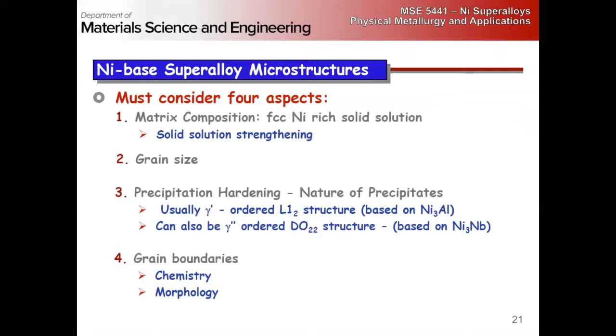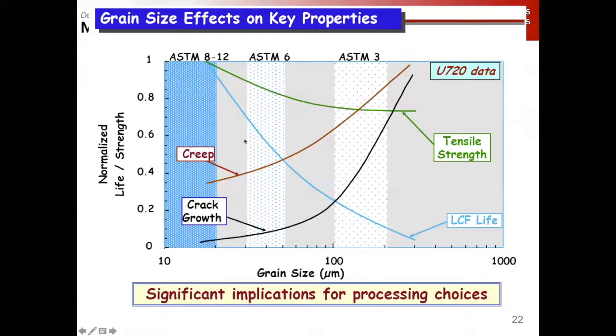So as we make the grain size larger, our creep life goes up, but our low cycle fatigue life plummets, right? And as our grain size gets larger, our crack growth rate goes up, and our tensile strength decreases a little bit. So our tensile strength isn't going to be a huge criterion with grain size. But this trade-off between creep life and low cycle fatigue life is going to be critical in thinking about how we design and process these. Right? So it's a balance and a compromise of properties.